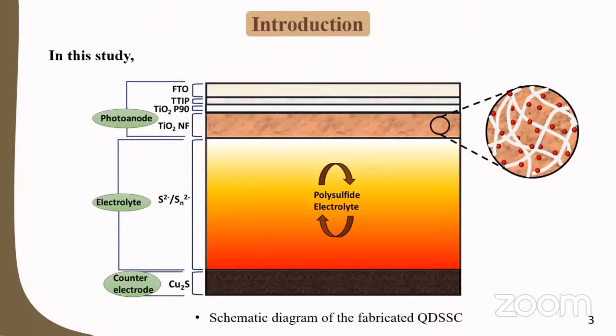Upon illumination, quantum dot is excited to a higher energy state and excitons are created. Due to the band alignment, excited electrons are injected to the conduction band of the TiO2 and the holes are scavenged by the electrolyte. Electrons diffuse through the mesoporous TiO2 and reach the conducting glass substrate and then enter the external load to perform work. Then these electrons reach the counter electrode and regenerate the oxidized component of the redox couple in the electrolyte.